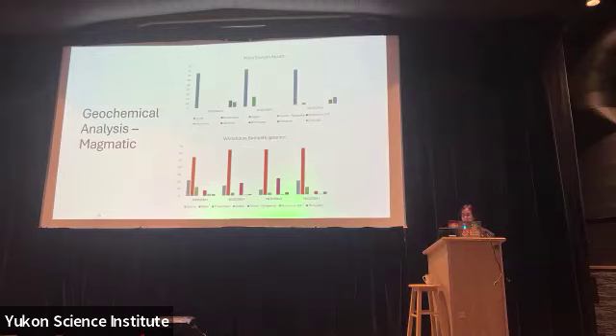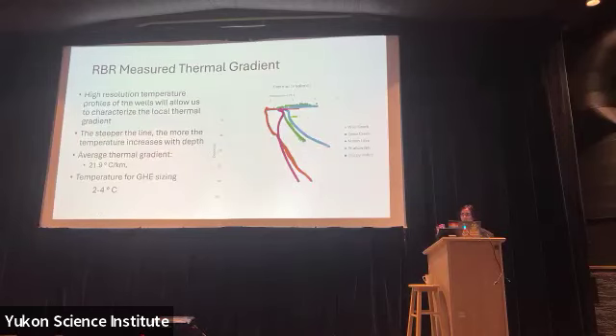And then, of course, the basalt formation is highly influenced by the porosity and permeability that we see within that formation. And the batholith had a fairly high thermal conductivity, which was similar to what we saw within the sedimentary rock formations. So within those formations, the granitic and the sedimentary rock formations, we have a global mean of about 2.5 watts per meter Kelvin. And then within the porous formations, which would be the basaltic formations and the saturated sediments, we have a global mean of about 1.5 watts per meter Kelvin. And this is really important information that we can use in sizing potential ground source heat pump systems in the